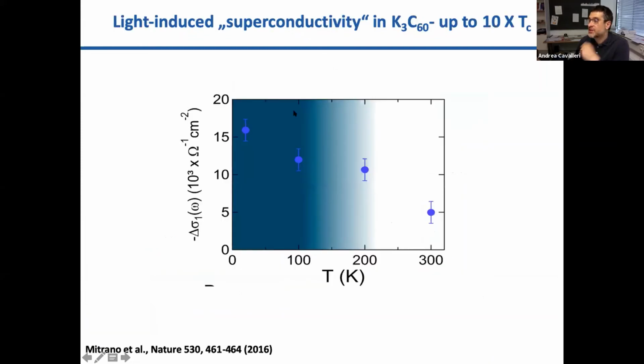And what he showed was that, depending on how you define this putative light-induced superconducting state, you could convince yourself that the effect certainly was observed up to 100 Kelvin, and one would find a finite gap all the way to room temperature. So this is the data that was reported at the time.